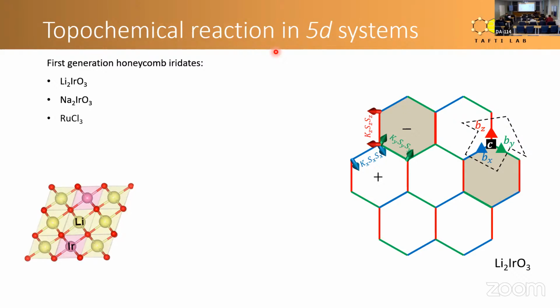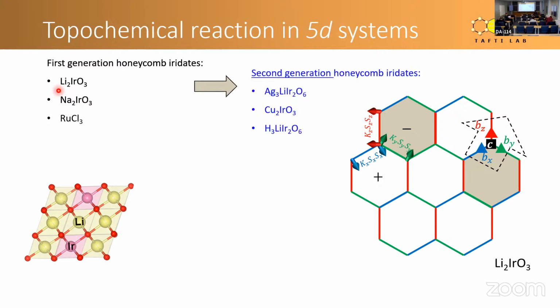And I'm going to give you examples of this kind of exchange reaction in 5D, 4D, and 3D systems. I start with the 5D. Now, the idea of a topochemical exchange reaction is that you start with a known template, for example, lithium iridate or sodium iridate. And what you do is that you change some of the cations, usually the cations that are between the layers. And by doing so, you create a new version of it.